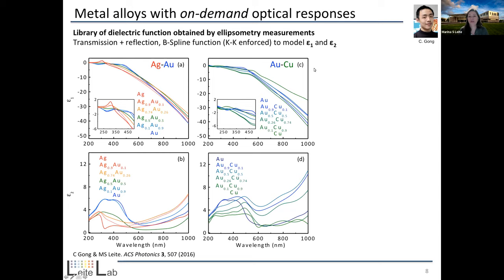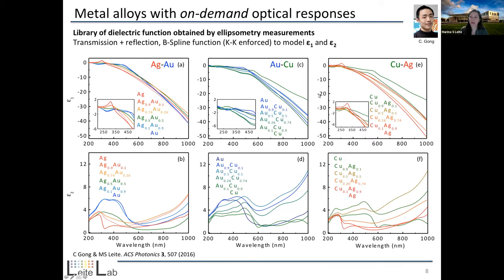So these are the results for gold and copper. I won't get into any details on that due to time. And then for copper silver, this is a really interesting system because we actually do not easily form a solid solution. It requires quenching, meaning decreasing the temperature very quickly after the deposition. However, this is really useful for us again to show that we can actually identify.